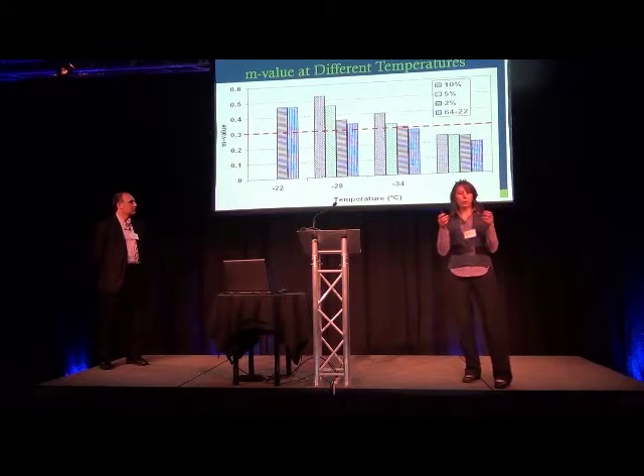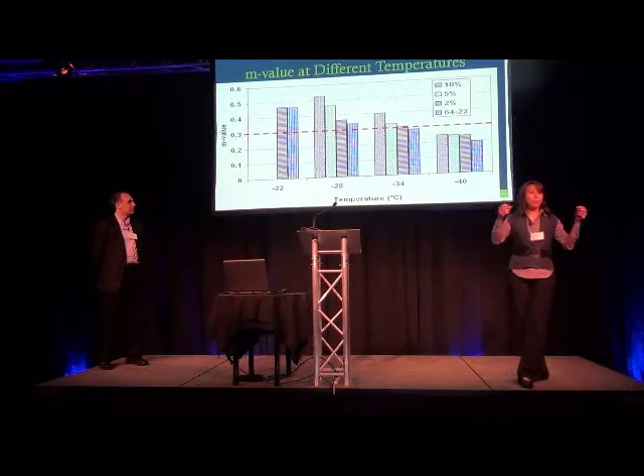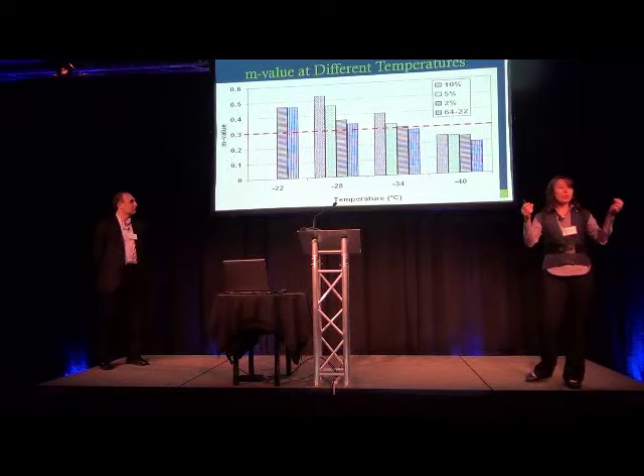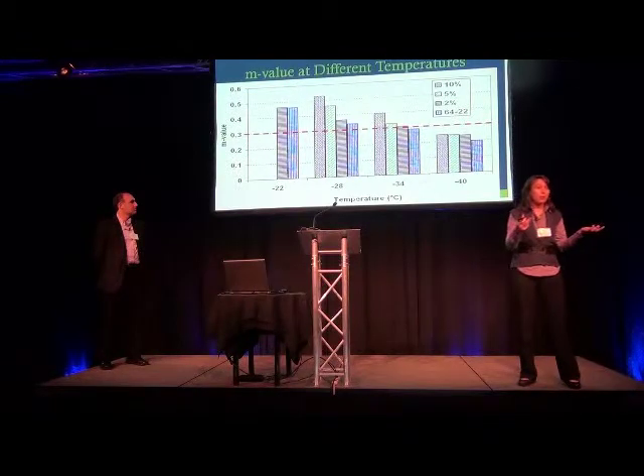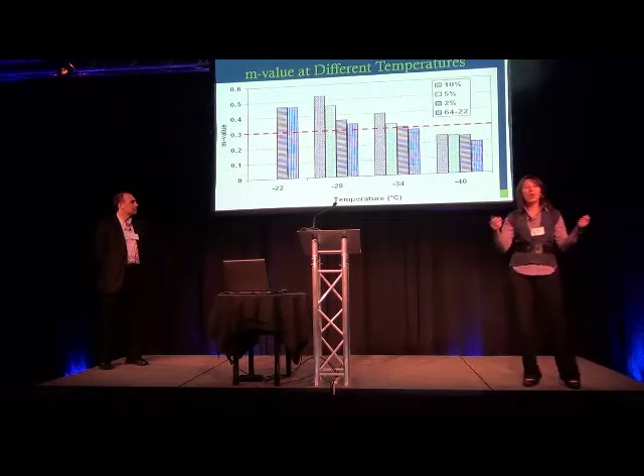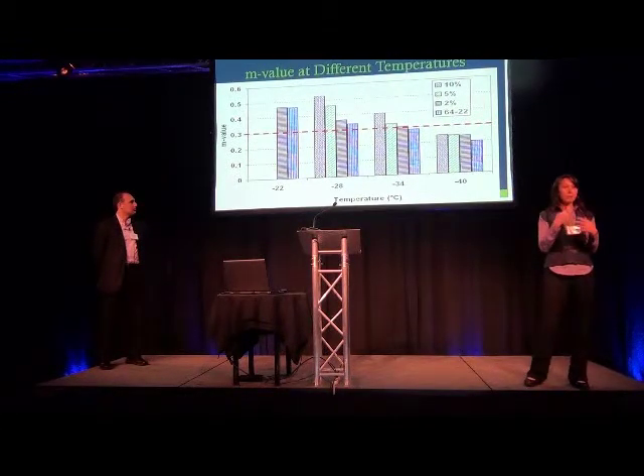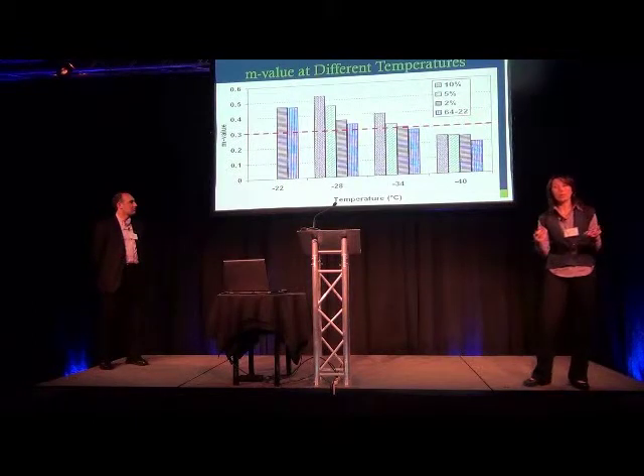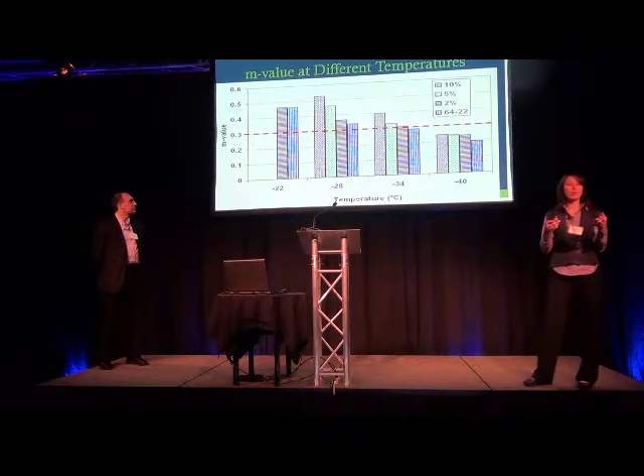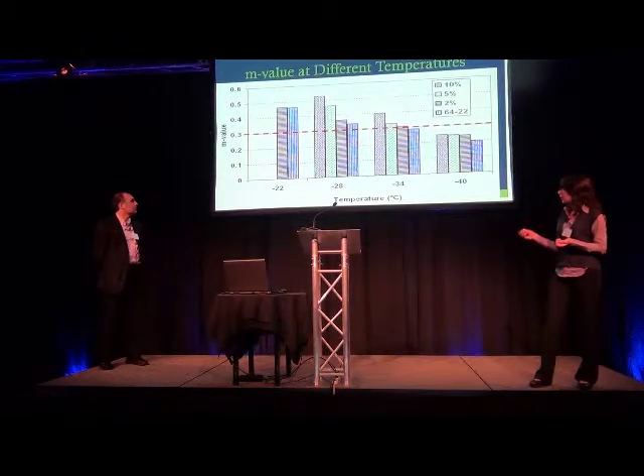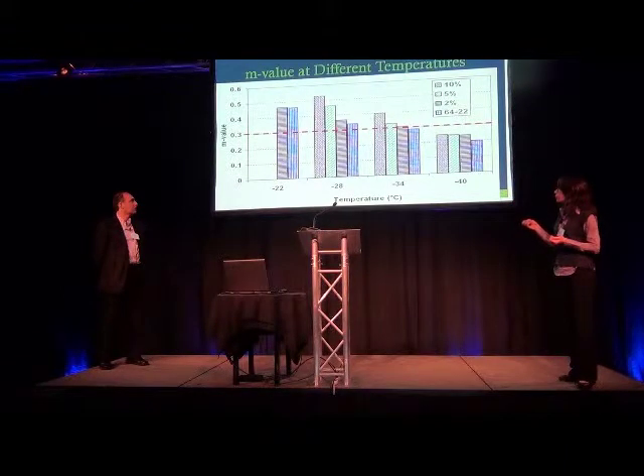If you imagine you have a steel bar or a concrete bar, a material, and you cool it down, it shrinks, and if you're confining it on the sides, you're building a stress within the material. So the only way for the material to release that stress is either to crack, which you typically see on the road because it wants to release the stress, or to deform. If it is compliant, if it's flexible enough to deform, it can release the stress without cracking. That's what we want in terms of asphalt, because in winter when it shrinks, we want it to be able to release those stresses without cracking. So the higher m-value is better for us, but basically the cutoff, the threshold for the specification, is 0.3. So as long as you're above 0.3, you're good.